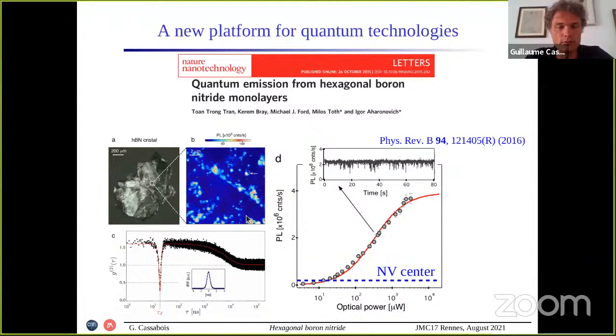If we do microscopy, we have a lot of hotspots, and using the usual techniques of quantum optics, by performing intensity correlation measurements, we could demonstrate that these isolated hotspots correspond to single defects that are extremely bright.